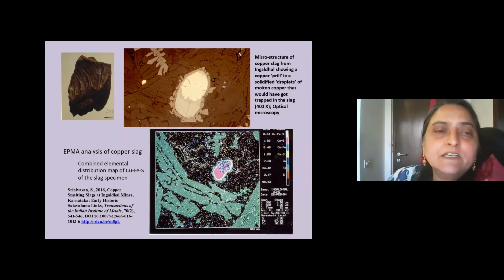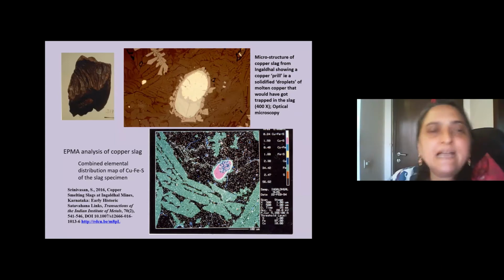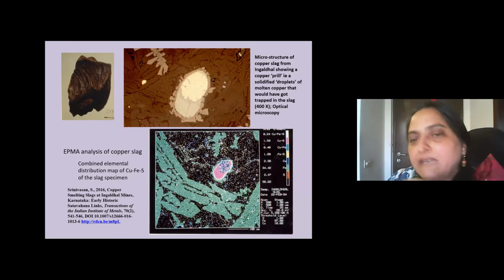So I had showed you some of the mining evidence from Ingaldhal, and here you're looking at what we call slag. This is tap slag in this case, and this is what floats to the top of the furnace, and which is analyzed here. You look at the microstructure, and you can see that the copper metal has segregated into these globules, solidified from the molten state, and then it also has this sulfide ring around it, which suggests that this was probably sulfidic smelting. And you also have this glassy matrix around it of the fayalite slag.